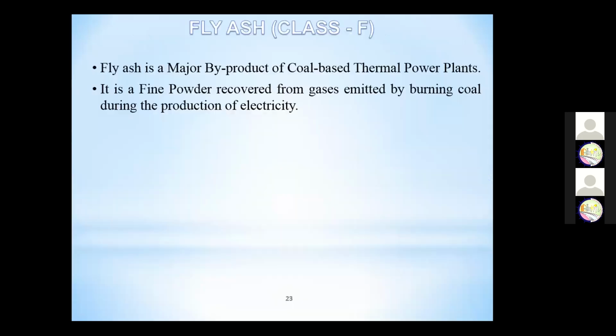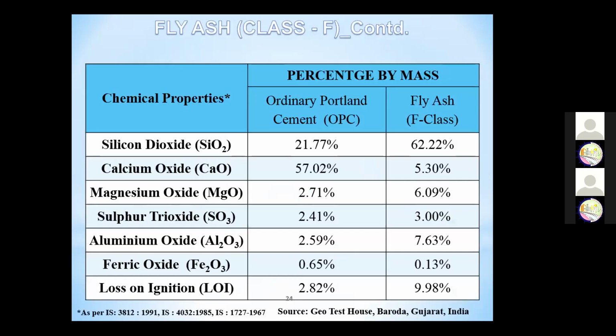Now fly ash is a major byproduct of coal-based thermal power plants. It is a fine powder recovered from the gases emitted by burning coal during the production of electricity. So we all know this is a coal-based thermal power plant byproduct. This is a very important table regarding the comparison between ordinary Portland cement and class F fly ash. Here refer to silicon dioxide SiO2: 21.77 in cement and 62 in class F fly ash, so almost 3 times more, and the CaO in the cement is 57, but in fly ash 5.3.